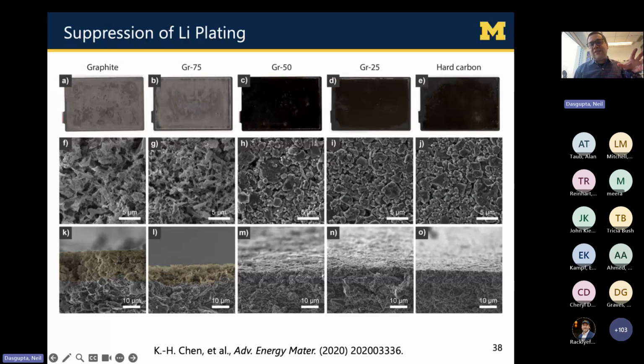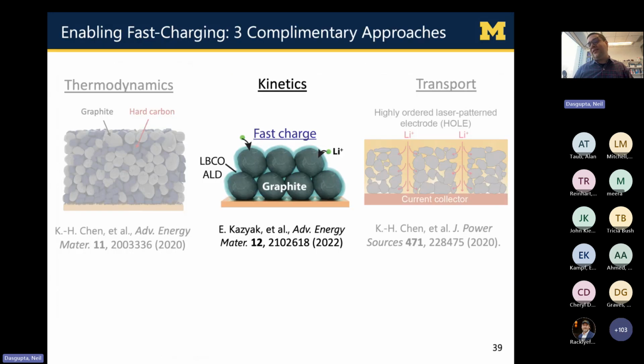Pure graphite under fast charging, a lot of metallic plated lithium on the surface. Whereas by the time we get to 50-50 blend of graphite and hard carbon, we've pretty much eliminated that lithium plating, but still enable thick loadings and high energy densities. And this is an even simpler manufacturing solution. It doesn't even require that laser patterning. Just by simply changing the blends of the type of carbon, there's pathways to enable fast charge.